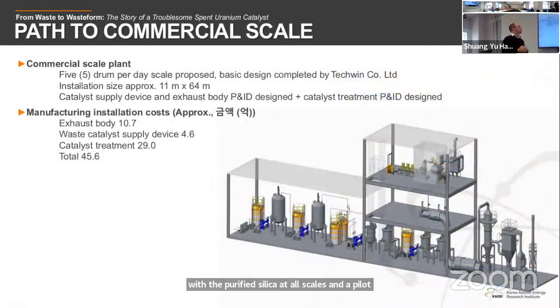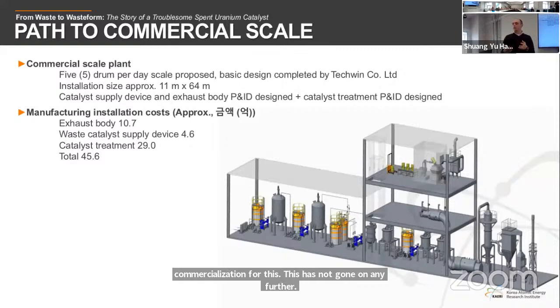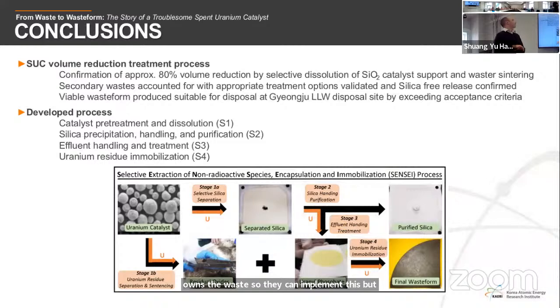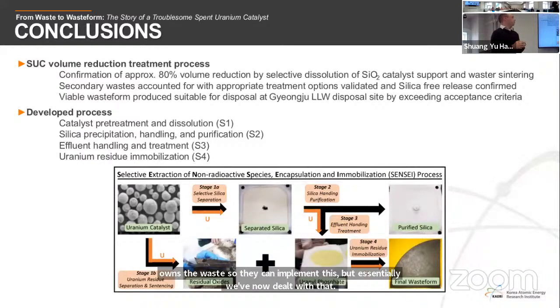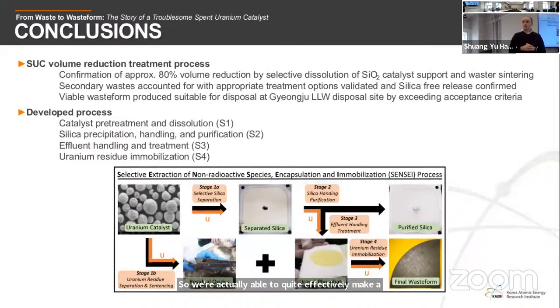This then allowed us to actually start looking at commercialization for this. This has not gone on any further because it's now been transferred over to the company that actually owns the waste so they can implement this, but essentially we've now dealt with that. So we were actually able to quite effectively make a reasonable process to take the waste, as I said, that was not suitable for direct disposal, and actually form a volume reduction process while also solidifying uranium and retaining it for final disposal.